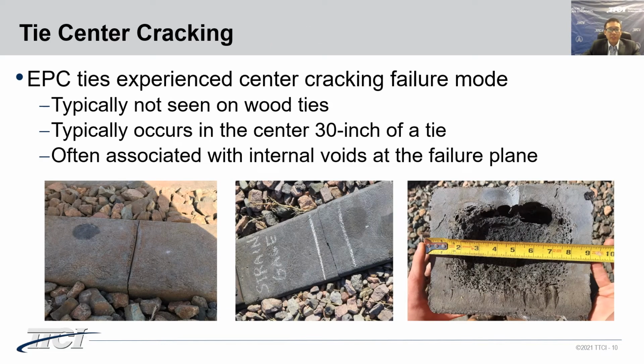In the next few slides, I will be focused on the development of a center fatigue test to address the center cracking issue. As I mentioned earlier, the failure mode is typically not seen on wood ties. The cracking occurs in the center 30 inches of the tie. According to the in-track observation, the center cracking failure is often associated with internal voids or defects in the tie center, as you can see in the photos here. Existing laboratory qualification testing in the AREMA manual has not proven its effectiveness in identifying this failure mode before in-track installation. This highlights the need for a more representative laboratory test.